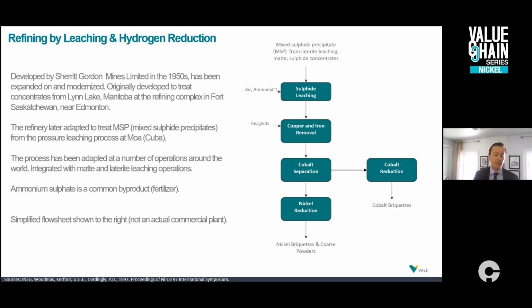Whether it's in Madagascar, Canada, Australia, Finland, it's been successfully commercialized quite widely. And after you generate a pure nickel solution and a pure cobalt solution, there are a series of vessels into which hydrogen gas is injected, and the hydrogen gas reacts with the nickel in solution to produce a nickel powder. And this isn't a very fine nickel powder like we talked about before.